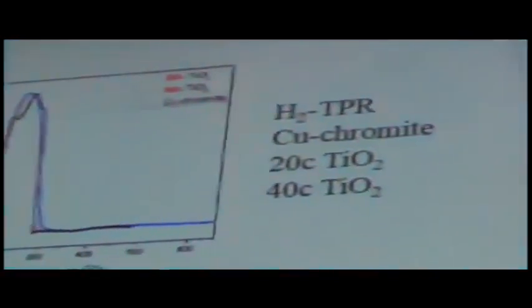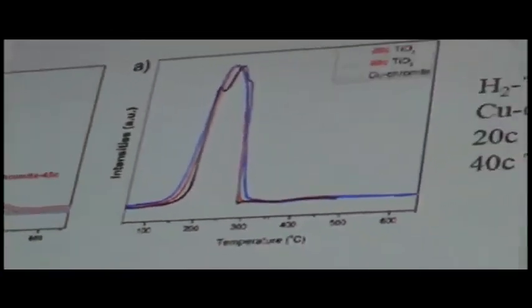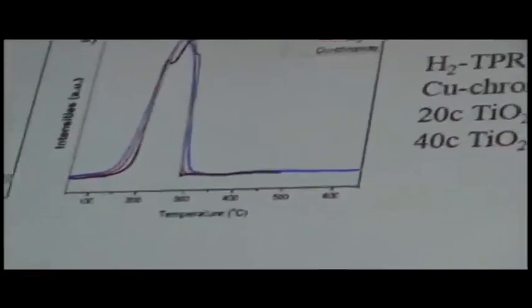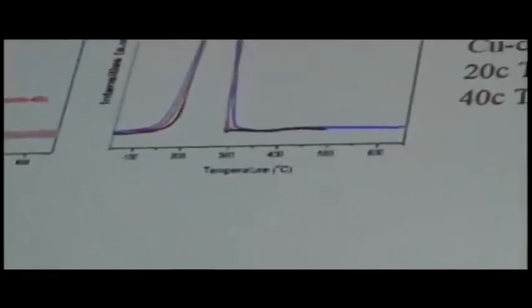If we look at the material which we do titania overcoating, though, you can see that all three curves overlap with each other. What you see there again is the copper chromite by itself, shown in whatever color that is. I guess it's blue. And the either 20 or 40 cycles of titanium oxide. We haven't changed the redox chemistry of the copper that we're interested in by doing the titanium overcoating.